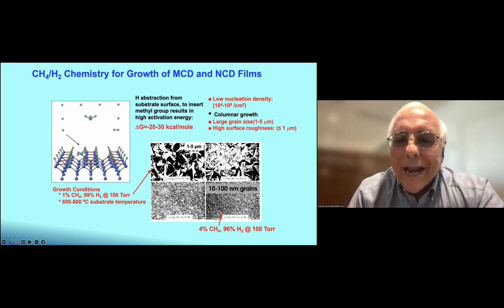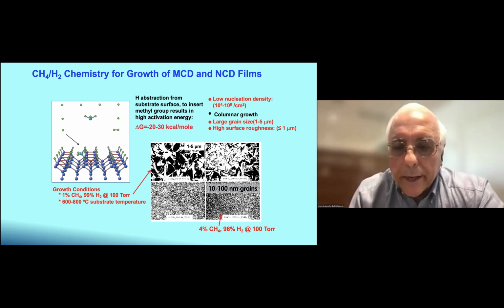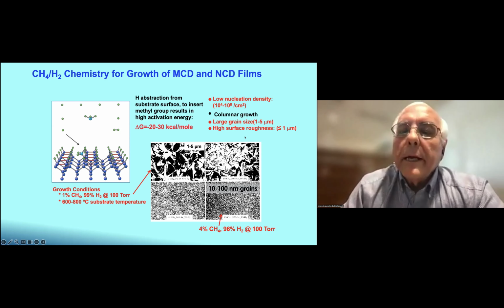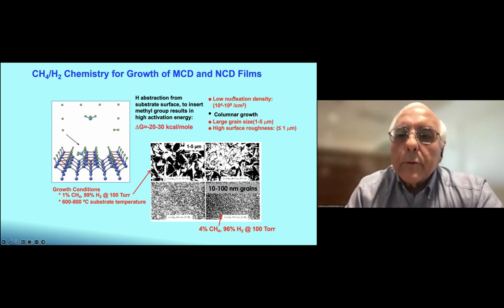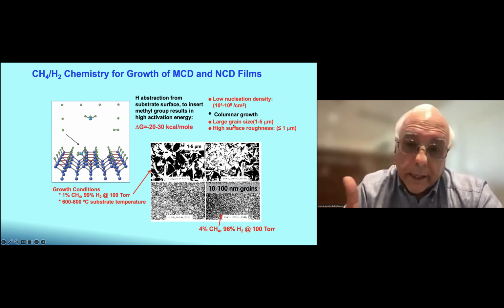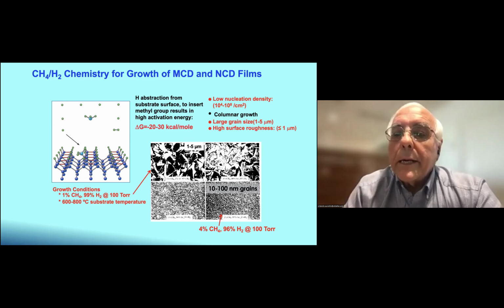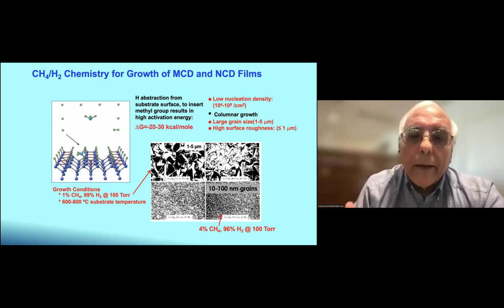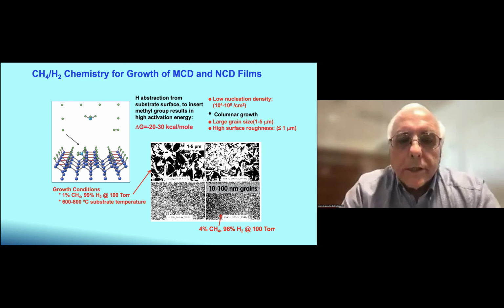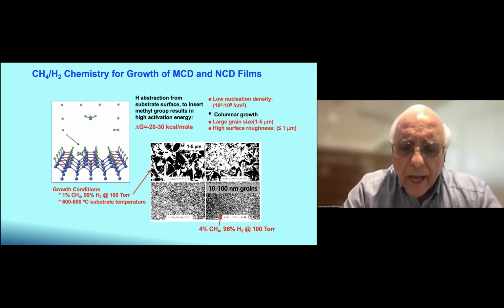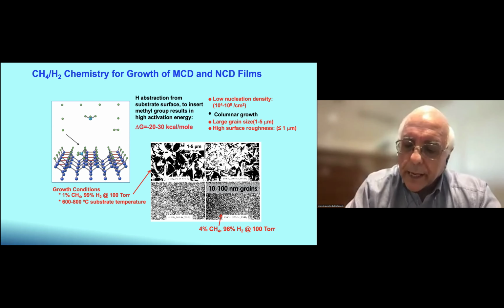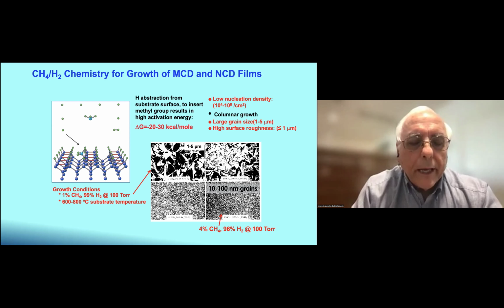And then when they were able to switch to 4% methane, 96% hydrogen, they were able to grow what they call nanocrystalline diamond, with a grain size of 10 to 100 nanometers. But when we started looking at that, we saw low nucleation density of 10 to the 4 to 10 to the 8, columnar growth, large grain size in the case of 1 to 5 microns, and high surface roughness. And we wanted to have a material with much smaller grain size and a smaller surface roughness. So that's why we started looking at an alternative and having a source of carbon without hydrogen.